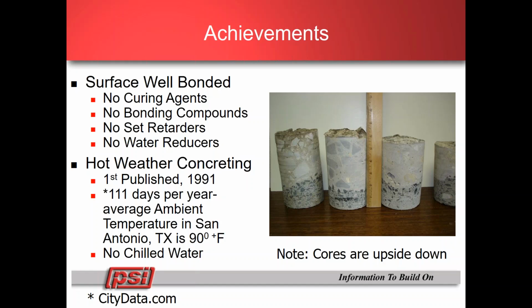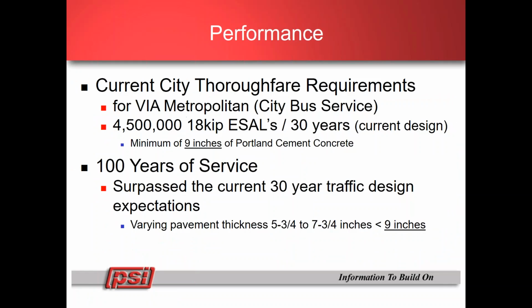We clearly see that these cores are upside down, but we clearly see that dense surface trap rock and the river gravel in the underlying portion. From published literature by the San Antonio, approximately 111 days per year, the average temperature in San Antonio is above 90 degrees, and there was no chilled water at the time of this concrete production, and yet they were able to place it, finish it, and get a good bonded two-course concrete surface that has lasted for 100 years. This is truly an amazing accomplishment.